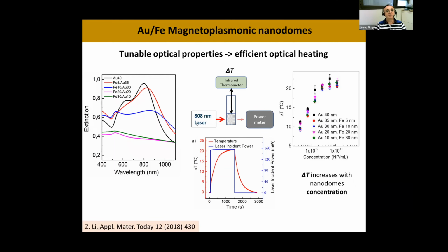The way we go about this is we have a suspension of nanoparticles inside the cuvette. We apply an 808 nanometer laser, and then using an infrared thermometer, we measure the temperature of the liquid. We see here that when we apply the laser, here in blue is the intensity measured at the power meter, the temperature of the water increases, and in about 10 minutes we can get an increase of temperature in the water of about 20 degrees.